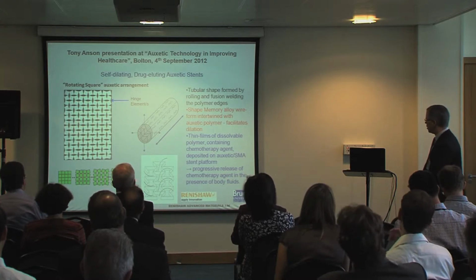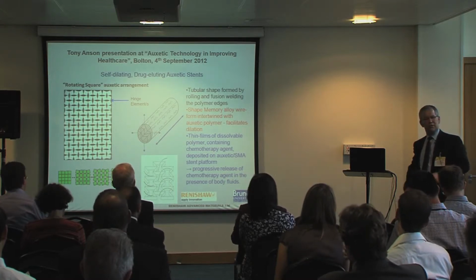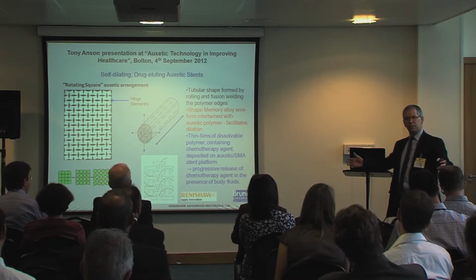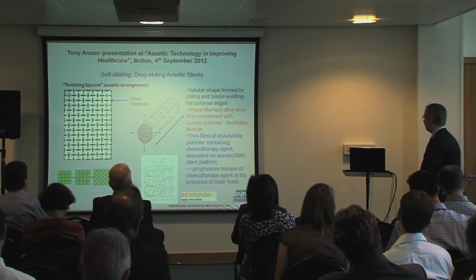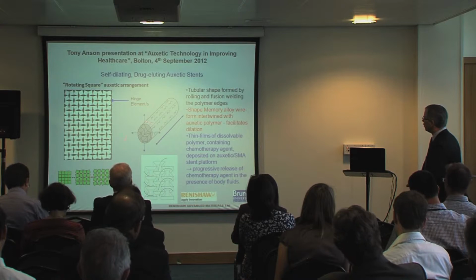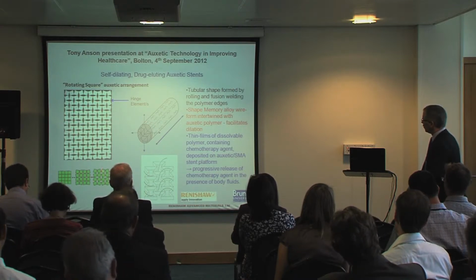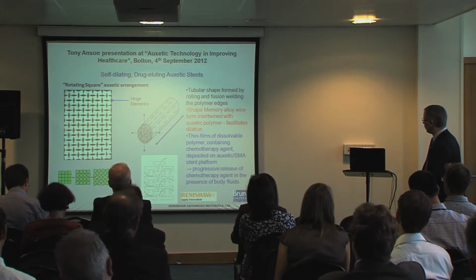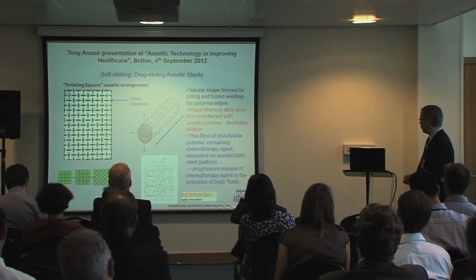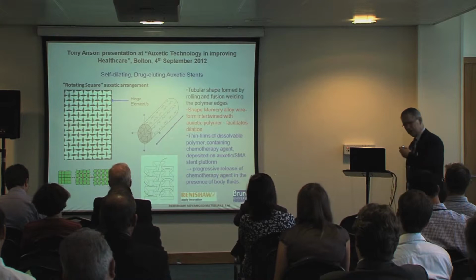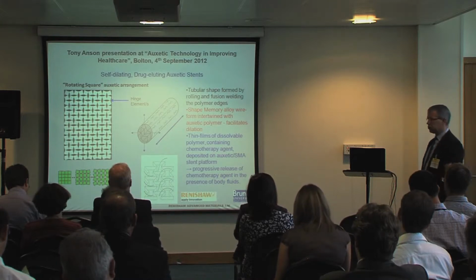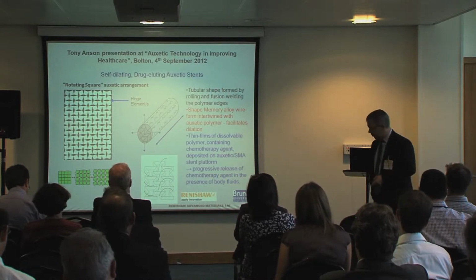He's incorporating a shape memory alloy material to give you large strain dilation mechanisms, and he's coating the polymer with the rotated square material with a polymer, a dissolvable polymer with a chemotherapy agent in there. So genuinely, I think, a multifunctional device there.